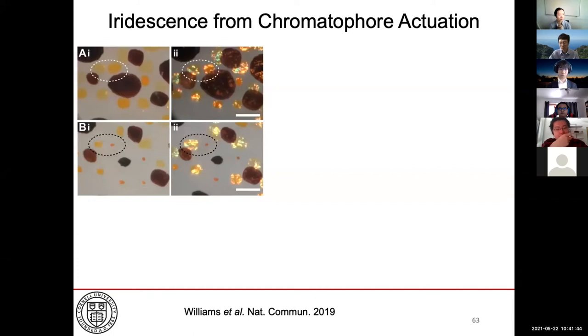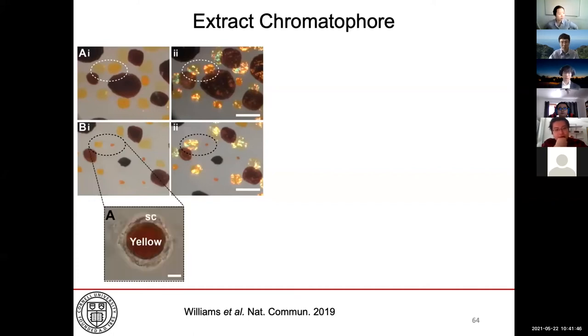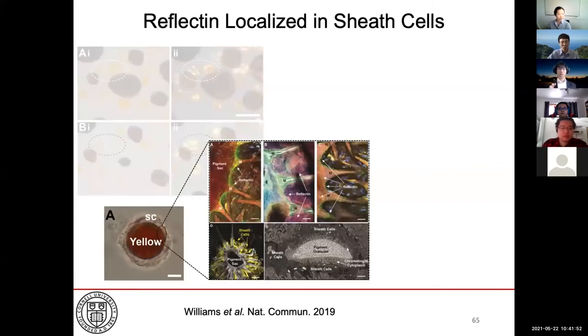metaphorical rabbit hole. So my experimental collaborators punched out and sorted the chromatophores according to their different colors, and then they were stained and imaged. And here we find a key piece of the puzzle, where a protein known as reflectin is found to be localized in the sheath cells that surround the pigment sac. And this is critical because reflectin is known to form periodic structures that function as a diffraction grating to disperse light for structural coloration.